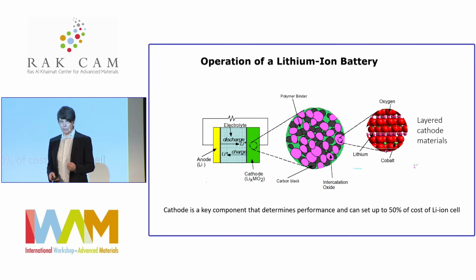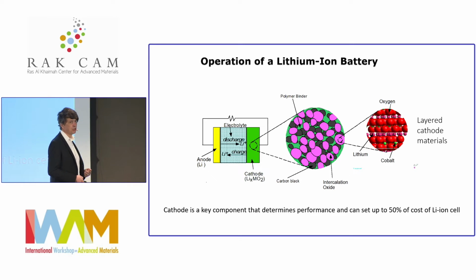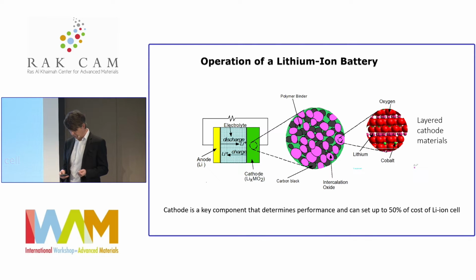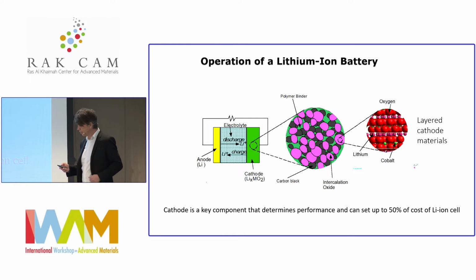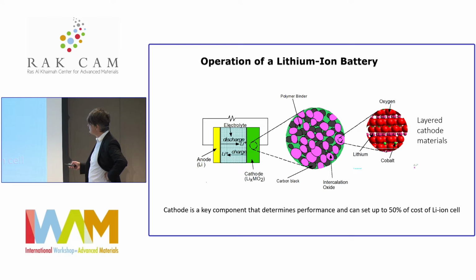Okay, so I want to explain to you the physics of where this problem comes from, and show you how fundamental science can actually solve that issue. Many of you are familiar, you saw Raphael's talk yesterday, of how a lithium-ion battery operates, and essentially they are intercalation systems. This is still the favorite system of choice, where you, in the cathode, intercalate lithium in a layered oxide typically, and there's this belief that these layered oxides are really good because lithium can diffuse easily into these layers. I'll show you that that's actually a bit of mythology that may not always be correct.